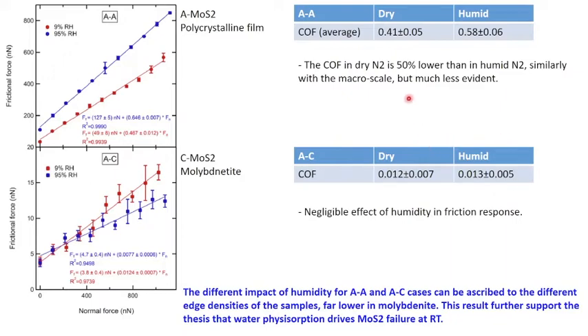So as expected, moving from amorphous to crystal structure, we have a very huge decrease of the coefficient of friction, because in this case we have the sliding of crystal against an amorphous condition with respect to the previous case. But the most important result is related to the fact that in the case of amorphous crystal coupling, there's no difference of the coefficient of friction from dry to humid condition.